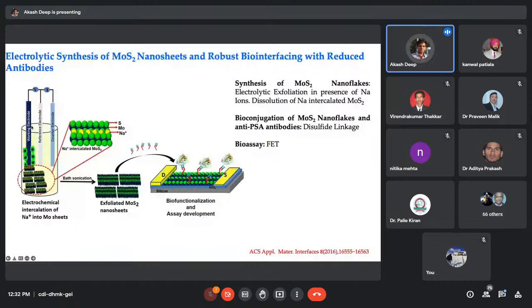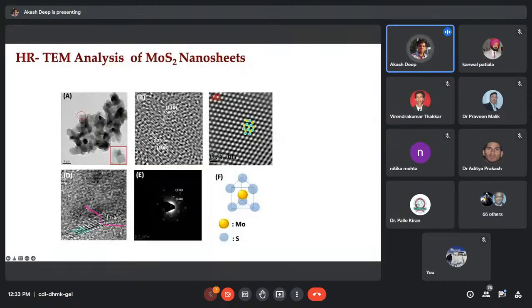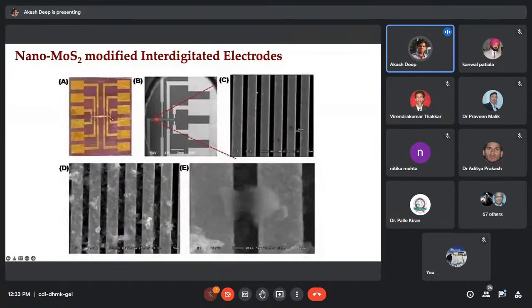TEM also confirmed the same thing. Around 7 sheets were formed with a total thickness of around 2.3 nanometer. And then these sheets were used to modify these field effect transistors. These field effect transistors also have different sensing regions, so a single chip can be used for around 16 to 20 analyses.